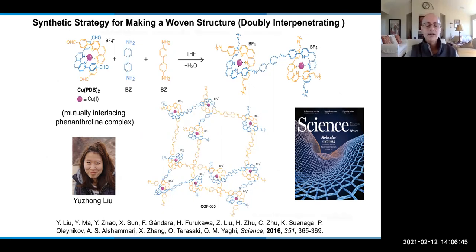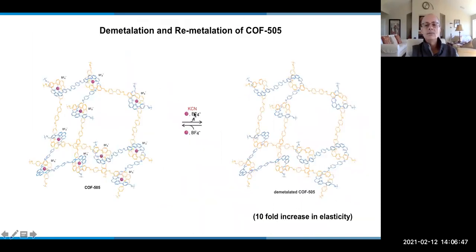And the very nice thing that she discovered is that you can remove the copper. You can add KCN and completely remove the copper from the structure to make the woven, truly woven COF. You can do this reversibly. You can do it as many times as you like. You go from a crystal to a non-crystal, not amorphous, but non-crystal, because anytime I add copper to this, it goes back to the crystal. I know the structure of this, even though it's a non-crystal.